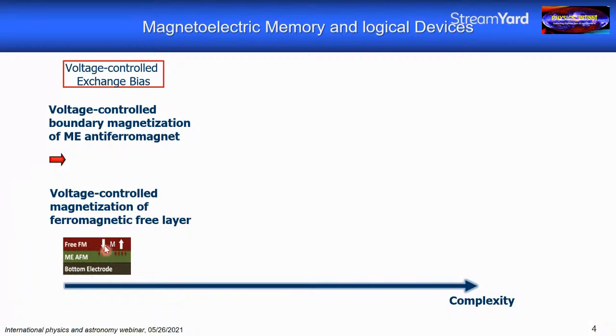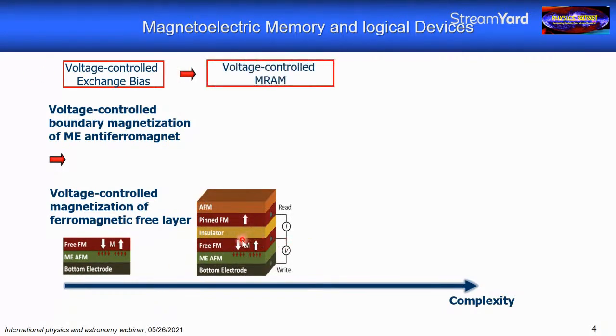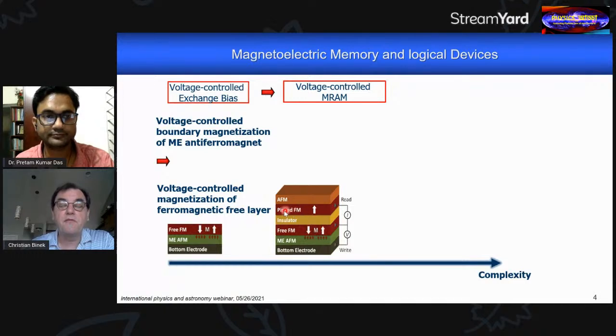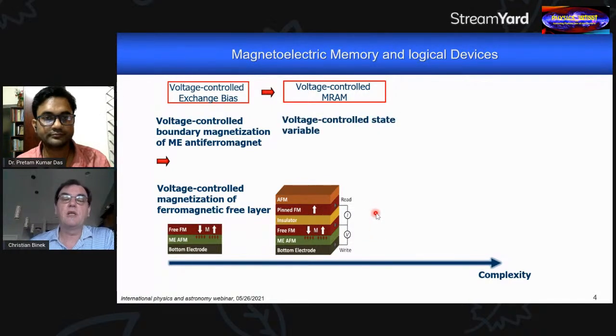Now you can put that into a more complex structure that has a tunneling magnetoresistance structure, made out of this layer that can be rotated, that can be switched, and a pinned ferromagnet here. And if you drive a current from here to here, then the resistance depends on the relative orientation of this magnetization. So that's a way to read out the information, the state variable that you wrote just by voltage, okay?